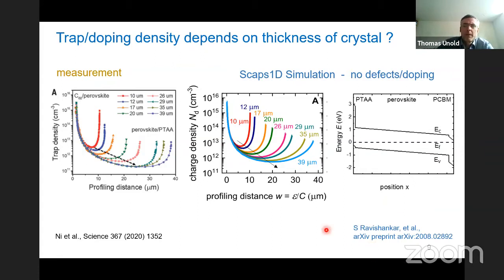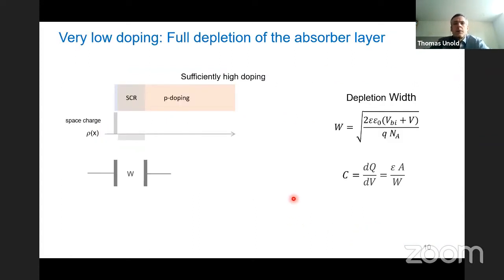But so we went further into understanding this. And so what we did is we looked at what you expect for very low doping. Before, I showed you a PN junction that was sufficiently doped like this. So you have a device, that's the device thickness, and then you have a space charge region that's part of the device. On silicon, actually, you have a 300 micrometer wafer and a space charge region that is 1 micrometer. So this is very far away.